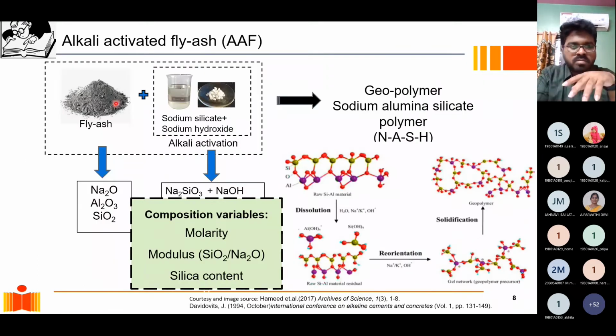So just to quickly introduce what I mean by alkali activated binders. There is a lot of excitement about these alkali activated binders where we produce cement-like materials by activating fly ash and slag. So we basically add some alkaline activator to fly ash and also some silicates into the solution. And what we get once it hardens are these cross-linked chains, which are called sodium aluminosilicate hydrate chains, and they're broadly called geopolymers. And these are totally cement-free binders. So basically starting from pure fly ash, using sodium silicate and sodium hydroxide, we're able to produce these binders, which are in a lot of sense stronger than cement, more durable than cement. So we are producing these materials which are made totally from waste materials, which give us good performance.